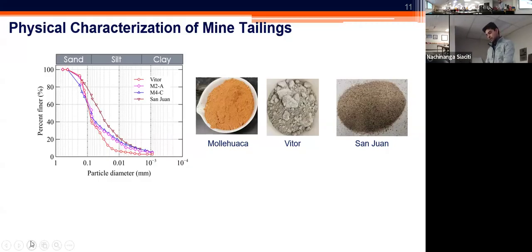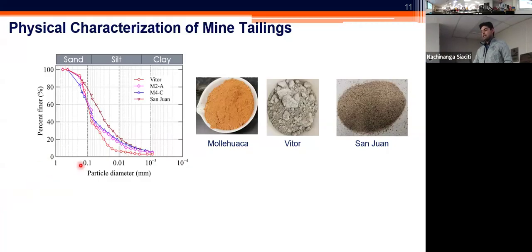So if I can use the laser option here, hopefully. Yeah, so sieve number 200 has the opening size of 75 microns. So you see that we have 40 to 60% passing of the tailings from that sieve size. But if you look also closely at the portion of the material with the size smaller than 2 micron, which is typically considered for the clay, we don't really have too much of the clay minerals within the material.